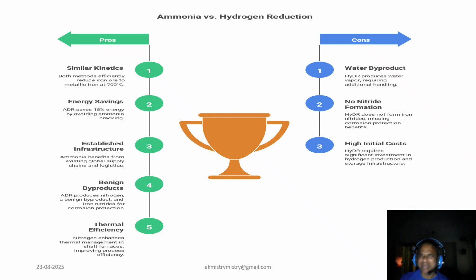Now coming to the comparison chart in this slide, where ammonia versus hydrogen reduction has been compared, and let's directly compare ammonia versus hydrogen reduction by looking at their pros and cons. For ammonia-based direct reduction, that is ADR, the pros include similar kinetics: both ammonia and hydrogen methods efficiently reduce iron ore to metallic iron at 700 degrees centigrade. As for energy saving, ADR saves 18% energy by avoiding ammonia cracking, which is a significant efficiency gain. Regarding established infrastructure, ammonia benefits from existing global supply chain and logistics, making it much easier to implement in any upcoming project.